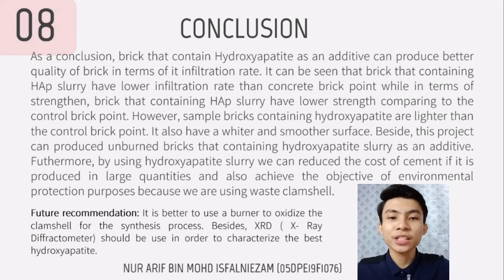As a conclusion, brick that contains hydroxyapatite as an additive can produce better quality brick in terms of its infiltration rate. It can be seen that brick containing HAP slurry has a lower infiltration rate than the control brick, while in terms of strength, brick containing hydroxyapatite slurry has lower strength compared to the control brick. However, sample bricks containing hydroxyapatite are lighter than the control brick. They also have a whiter and smoother surface.